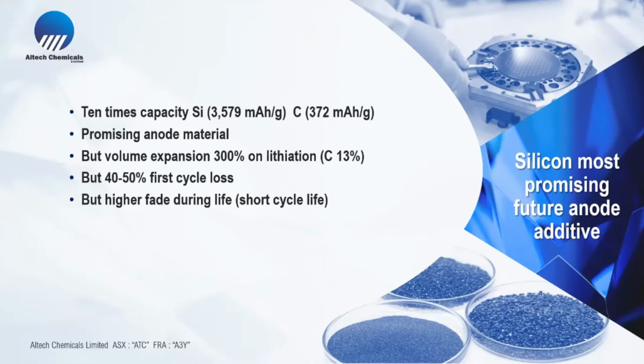Silicon has 10 times the capacity of graphite. As Tesla says, this is a very promising anode material. Now, if it's this promising, why isn't silicon used in lithium-ion batteries today? Essentially, there are three major problems. Firstly, the silicon expands 300% in volume compared to carbon, which is only 13%, and it fractures. Number two is that the first cycle loss, instead of 10% like graphite, is probably closer to 50%. So essentially, there are so many sites that it can absorb lithium on, it takes out 50% of the lithium inventory. And thirdly, it's got a higher fade during the life of the battery.